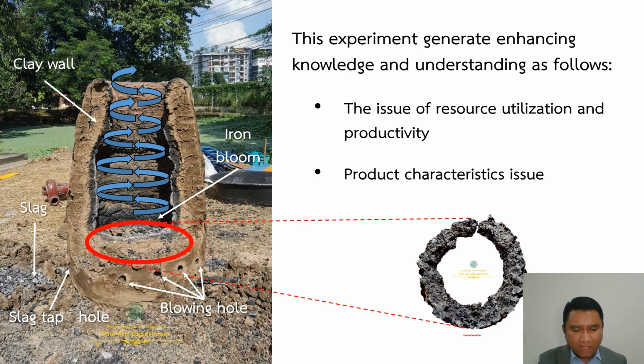Second, product characteristic issue. The process of aeration through blowing holes angled diagonally at 30 degrees creates a spiral of air inside the furnace. As a result, the steel will accumulate at high temperature until it forms a lump of iron bloom that has a ring shape. From the product appearance, it is therefore a preliminary archaeological assumption that this is the iron bloom product of the ancient iron smelting furnace site in Lee Basin, northern Thailand.